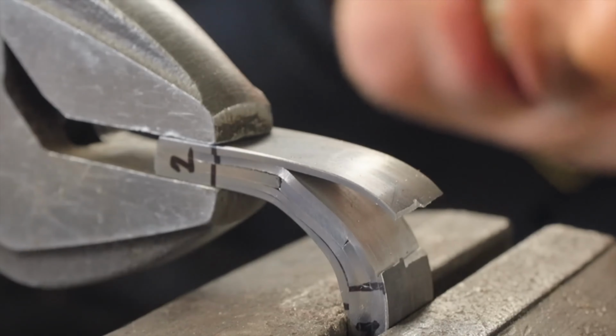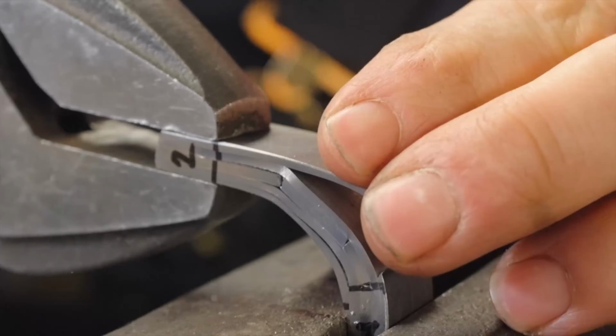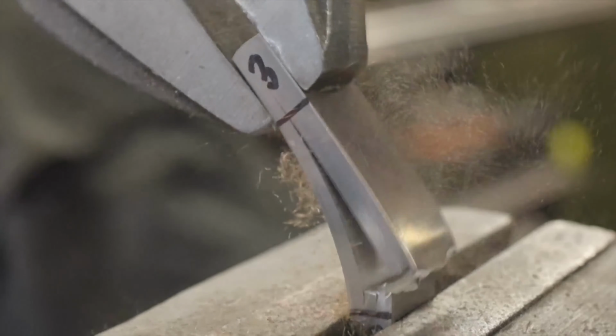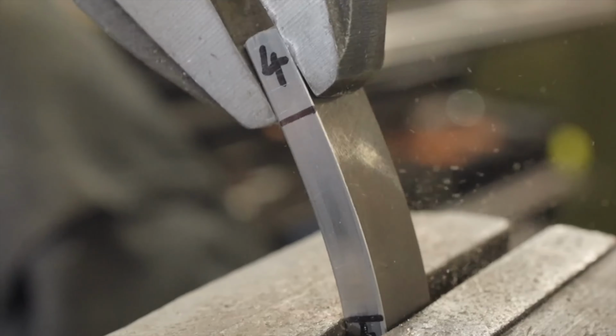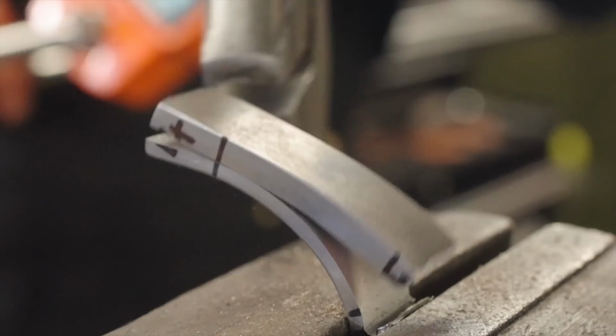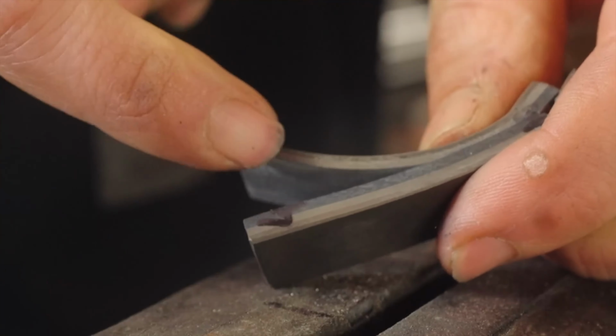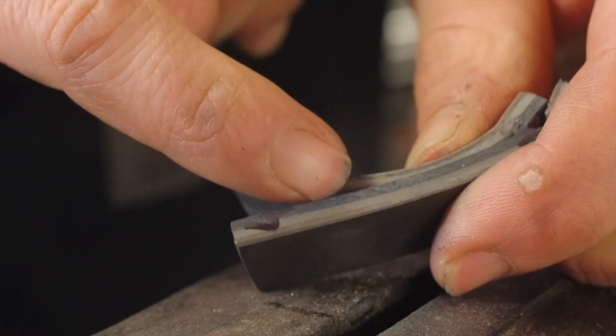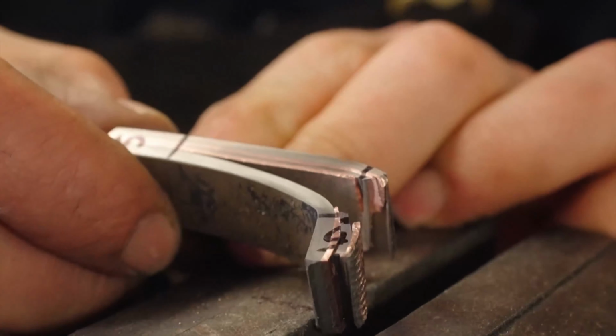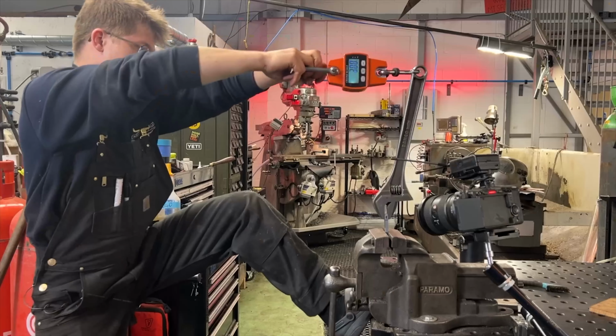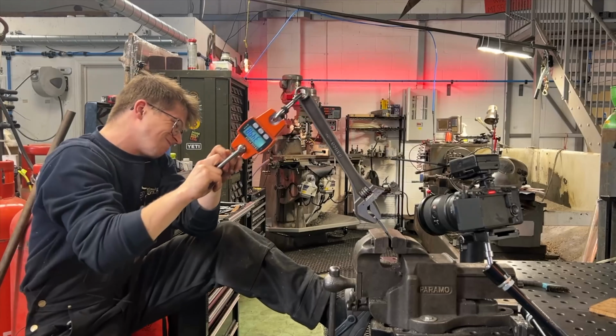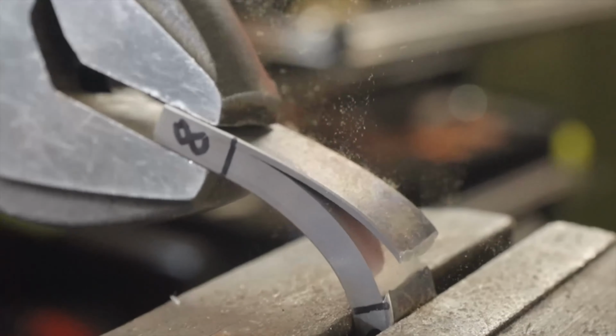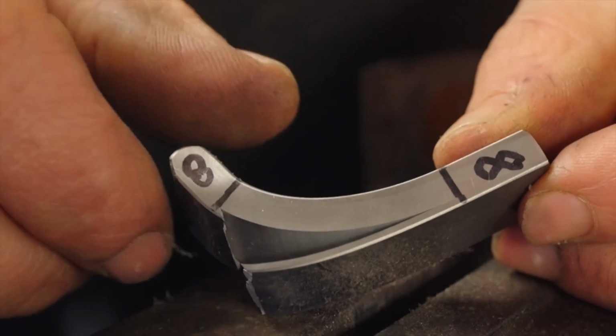Oh, broken the titanium. Oh, there's plenty of delamination though anyway. Madness. Oh, that was bad. No longer attached. That was a delamination between the nickel and the steel. Poor thing. We're obviously not doing 6 and 7. 8, our titanium control. Broke at the grade 5, grade 2 interface.